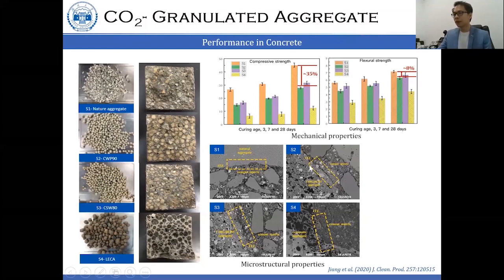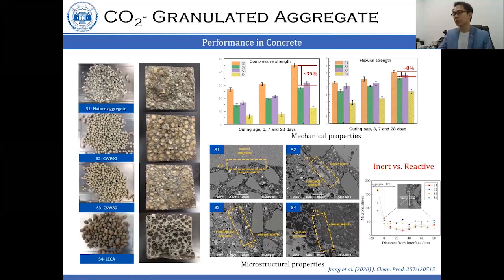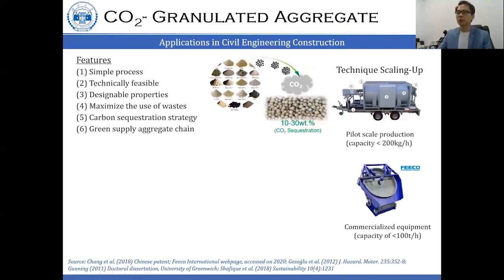So we can see there are obviously 2 different regions for the natural aggregate concrete. However, for the aggregate we produce, the shell layer might have some reactive material, including the calcite. They could have a further reaction with the new cement to improve the bonding between the layers. So this is also proved by the micro hardness result. So a bit on the applications.